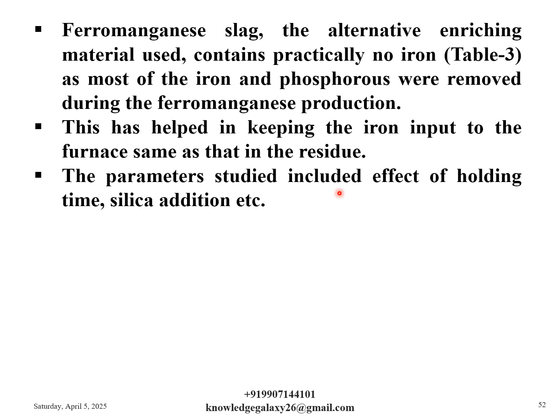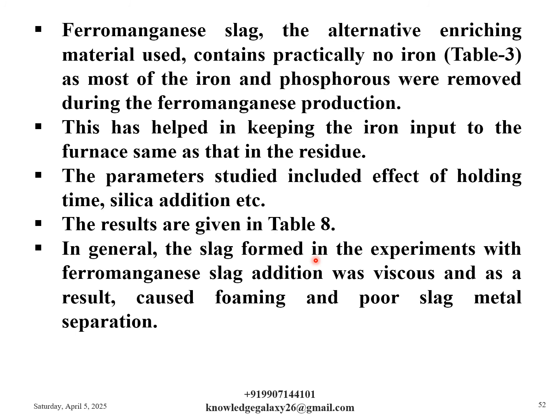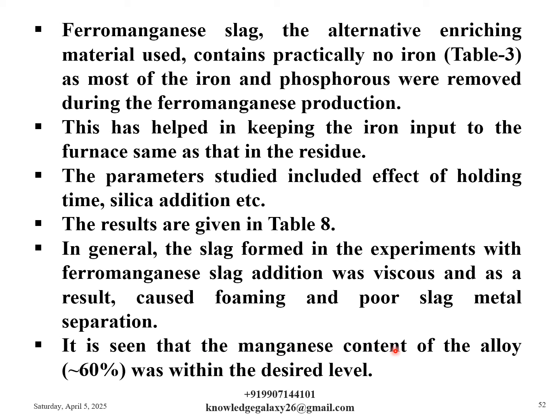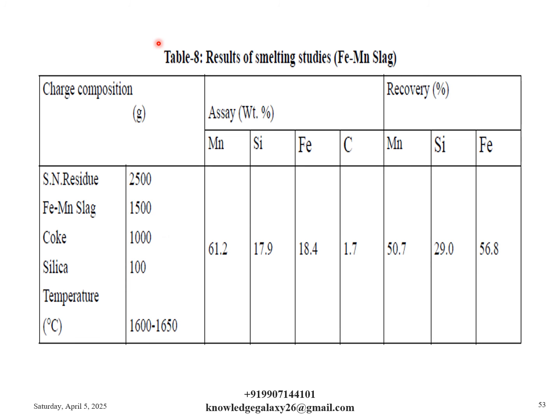The parameters studied included effect of holding time, silica addition, etc. The results are given in table 8, which is shown in the next slide. In general, the slag formed in the experiments with ferromanganese slag addition was viscous and as a result caused foaming and poor slag metal separation. It is seen that the manganese content of the alloy, equivalent to 60%, was within the desired level. So this is the table 8, which shows the results of smelting studies for ferromanganese slag addition as enrichment.